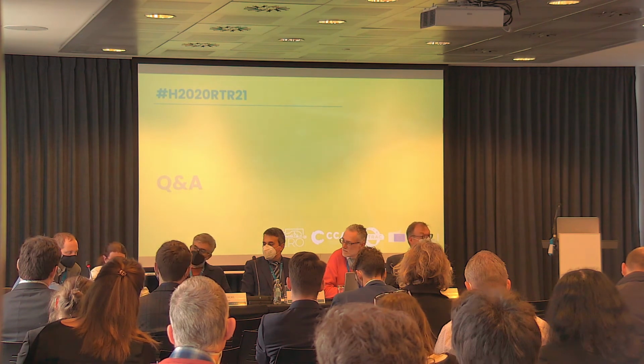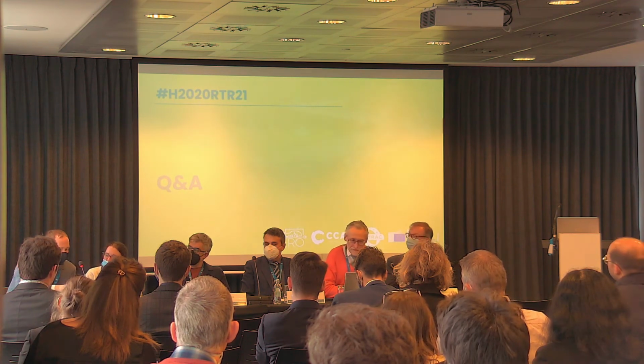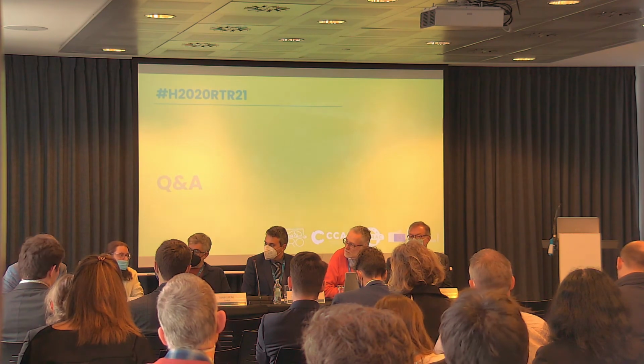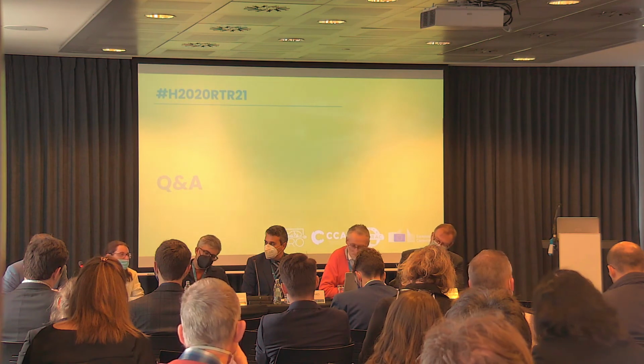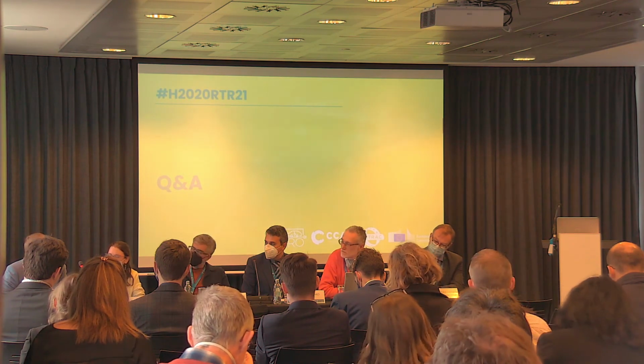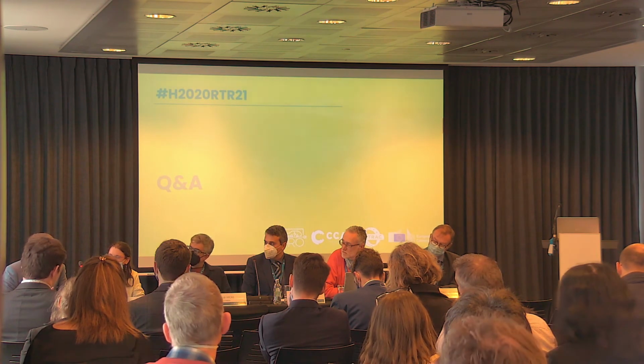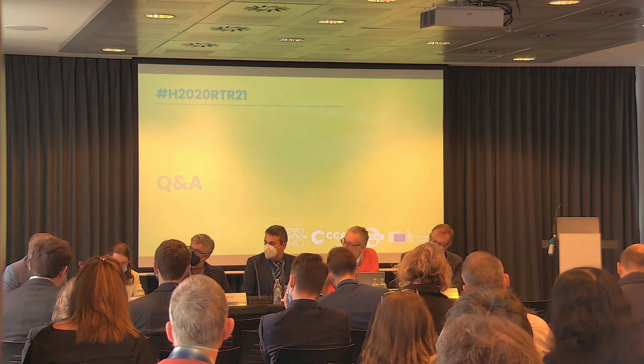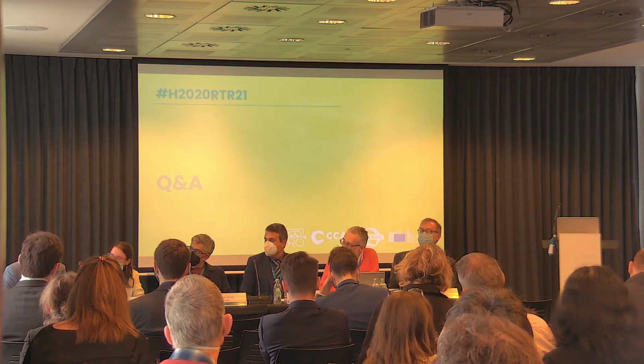Okay, so I will go for lithium sulfur. In the third project, the Alizé project, I believe you have the link in my presentation, we did module on pack. For lithium ion, the better the pressure, the better it is. For lithium sulfur, it is breathing. So the strategy that we used for the module manufacturing was to give space between the cells and let them breathe. It is a bit difficult because for the lithium stripping and plating, the lithium metal, it is better to apply pressure, but for the sulfur, you do not apply pressure. This is something that I did not show, but with different electrolytes and different types of cathode, in some cases you have to apply pressure, and in some cases you do not.